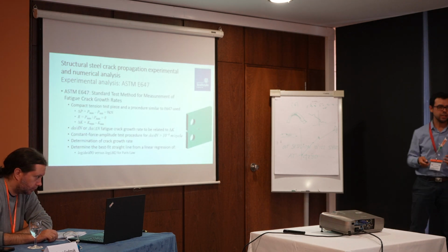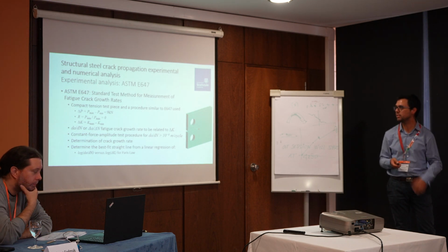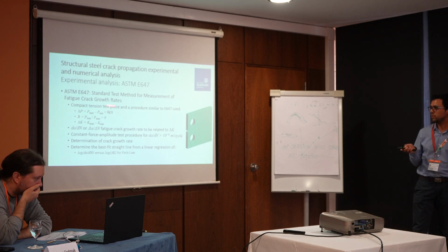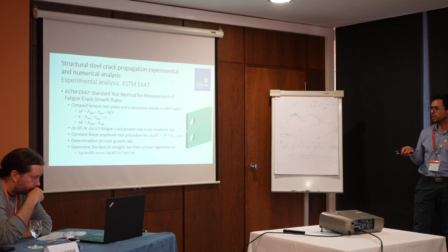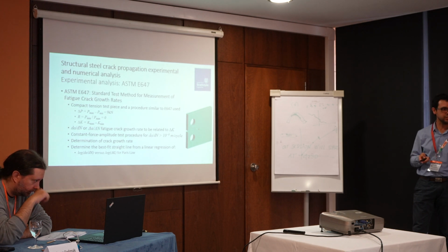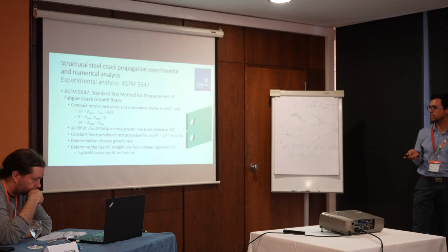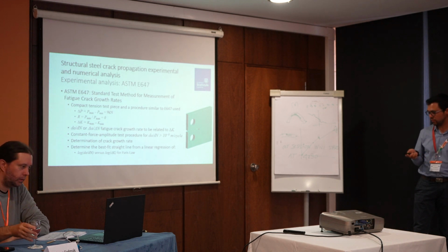So, as I said before, our study was based on the ASTM E647 procedure. Here, one of the things that I'd like to highlight is that we use a load range of 9 kilonewtons, as I said before, and a load ratio of 0. Also, the idea here is to try to obtain the stress intensity range using this methodology in order then to get the parameters for the Paris law.